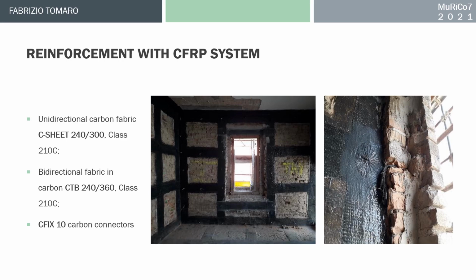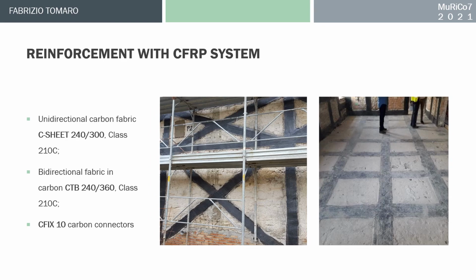The reinforcement interventions with the CFRP system adopted for the structural consolidation of the Palazzo della Ragione are a reinforcement system in unidirectional carbon fabric with a grammage of 300 grams per square meter applied with epoxy adhesives, and a 360 grams per square meter bidirectional carbon fabric reinforcement system, also applied with epoxy adhesives, arranged at an angle to perform shear reinforcement. The consolidation with the unidirectional carbon fabric of 300 grams per square meter involved also the floor as well as the load-bearing walls of the building.